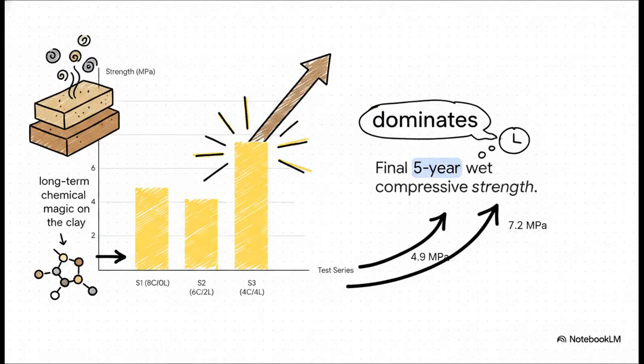The ultimate payoff happens right at year 5. The S3 series, that's the one with a perfectly balanced 4% cement and 4% lime, just utterly dominates the standard mix. It reaches a massive 7.2 megapascals of wet compressive strength, compared to just 4.9 for the cement-only mix. The cement provided the early structural integrity, which basically gave the lime the time and the perfect environment to work its long-term chemical magic on the clay.